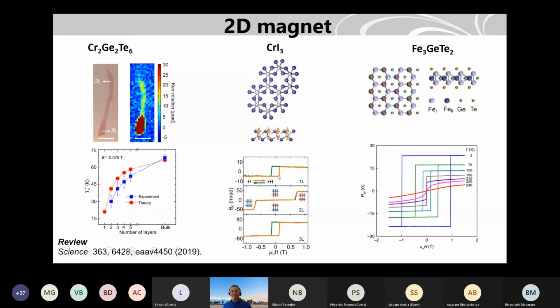So if you see, the single layer is a ferromagnet with a hysteresis loop, measured again with a Kerr microscope because it's a semiconductor. When you go to bilayer, it behaves as an antiferromagnet, so you don't see that hysteresis loop. But when you go to tri-layer, then again magnetism develops. So it has layer-dependent magnetism. That's quite interesting. And finally, FGT, iron germanium telluride, is a metallic ferromagnet.